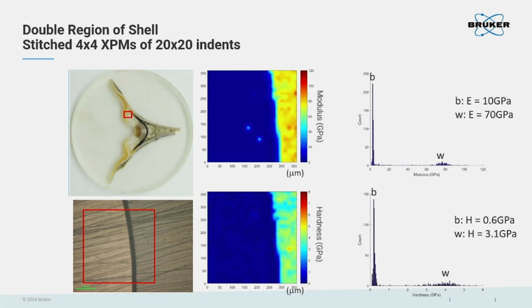So besides the maps, we can also have the histogram to see the peak value for these two components, for example, here. So we can see that this is for the higher modulus, which represents the mechanical property of elasticity of this component on the right-hand side for us. The mean value of the modulus is around 70 gigapascal. But on the other hand, if we take a look at the peak on the left-hand side, the average value for modulus is only 10 gigapascal, distributed in this region.